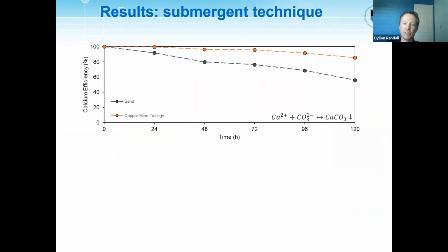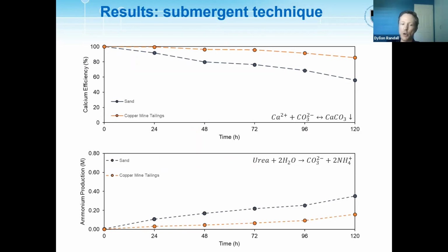And so here are some of the results. What you see here, we use the calcium as an indicator of the fact that the reaction is occurring, because when we have a reduction in the calcium concentration, it means calcium carbonate is forming. So what this graph shows us is that there's a gradual decrease in calcium for the sand, but a slower decrease when we're using copper tailings. In a similar vein, you could also use the ammonium production as an indication of your urea degradation. And we see a similar trend here, where the copper tailings have a slower gradual increase in ammonium production.